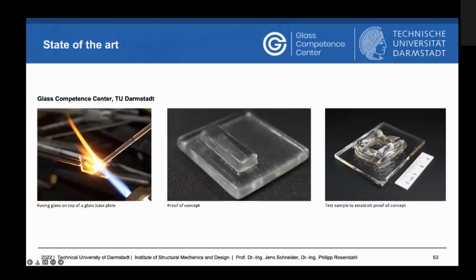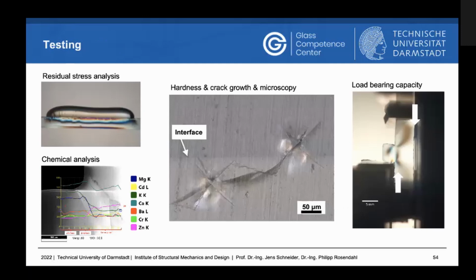Looked like this, or like this, I think is even a bit earlier. Not very delicate structures, but it is proofs of concept that you can put to a test. You can investigate the residual stresses in the connection between the melt-on and the glass pane that is shown below. This is done with photoelasticity methods. We've analyzed the chemical compounds in the transition zone between added structure and the glass pane. We've looked at cracking and how cracks might travel through or along the interfaces of printed structures.